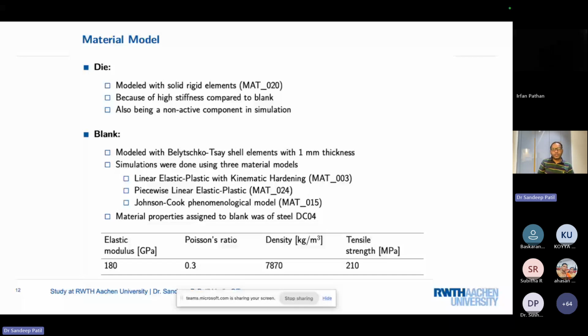The blank is what we are interested in, for which we use the Belytschko-Tsay shell element with 1 millimeter thickness. We tried other shell elements also, but as you can read in the details, this Belytschko-Tsay shell is the element type which is perfectly suitable for our high-speed method. Simulations were done using the material models MAT03, MAT24, and the Johnson-Cook material model.